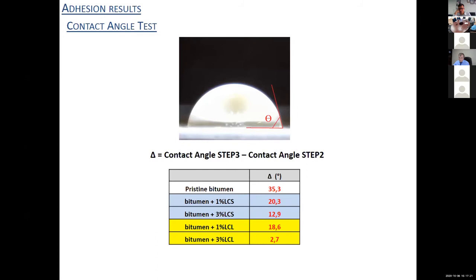These results shown in the table confirmed that the additives, solid and liquid, are excellent adhesion promoters, and they are similar to the boiling test results. In particular, the results of the liquid additive are excellent in comparison with the pristine bitumen, and they are better in comparison with the bitumen modified with the solid additive.